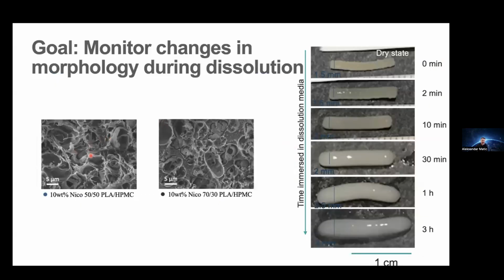So here are SEM images of two different formulations, one with equal amounts of the two polymers, and one where we have a little bit more of the PLA phase. And you can see that the morphology changes quite a lot. These images are made after leaching out the HPMC phase, so what you actually see is the PLA phase that is left. To the right, you see the extruded strand. So this is the formulation together with drug inside, the two polymers.